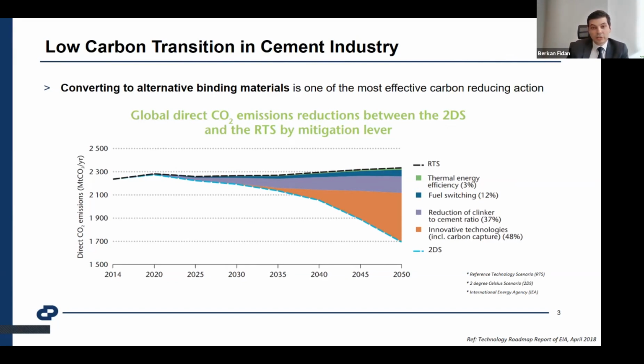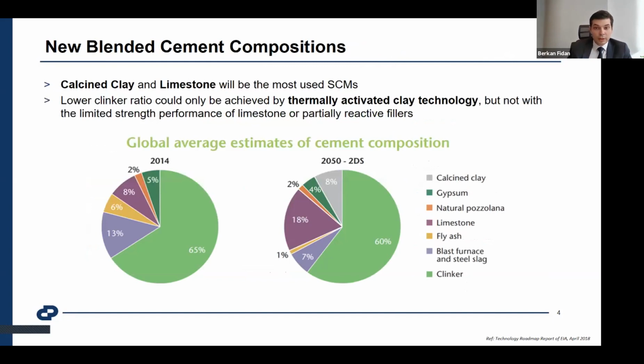The second most effective one, with 37% of this decrease, is reduction of clinker. And that's the reason we focused more on the cementitious materials, to change the content of clinker in the cement and to decrease the carbon effect. Again, this is shared from the International Energy Agency roadmap. It's given here. As you can see, it's data from 2014, but it's nearly similar for these years also.